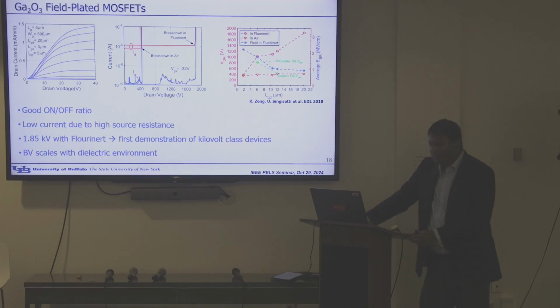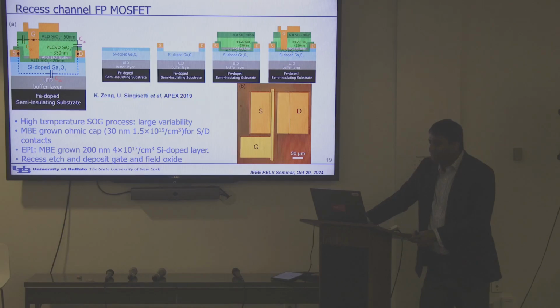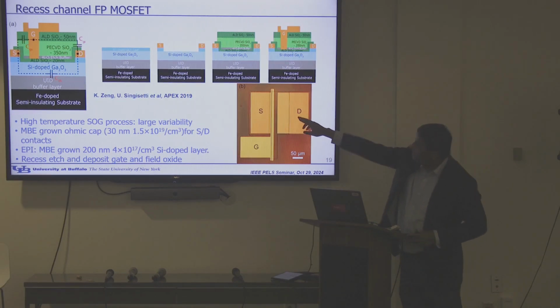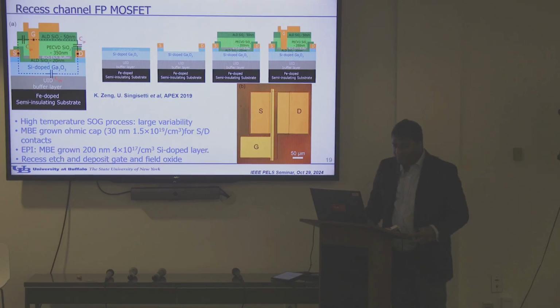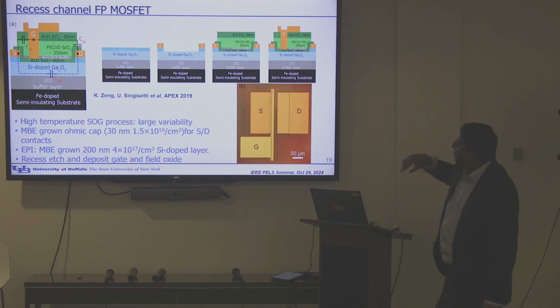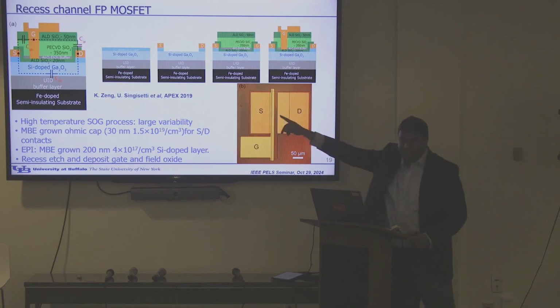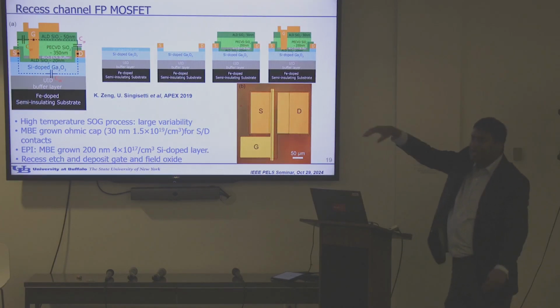We had some difficulty in the SOG doping. Then we switched to a different process where we start with the N plus layer, as you can see here in the center there. So we start with the N plus layer, the dark blue layer here by MBE, and then we etch away the N plus layer by RIE, and then you form the device, which is same as the previous generation device. Only difference is how the N plus layer is formed, right? Previously we were doing spin-on doping, you spin coat it, and then you diffuse it by annealing. Here we start with the N plus layer and then remove it where you don't want it.